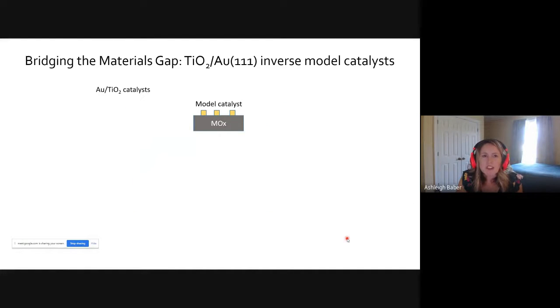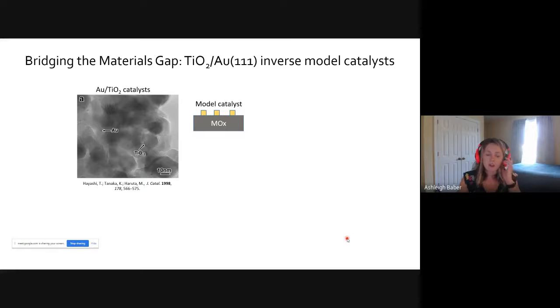In order to bridge this materials gap, we use model catalysts. And so you saw this image on the last slide, where you have gold nanoparticles supported on titania powders. And a model catalyst system that represents that would be gold nanoparticles supported on a bulk oxide of titania. In my lab, we flip that around. So we have nanoparticles of titania on a gold 111 surface.